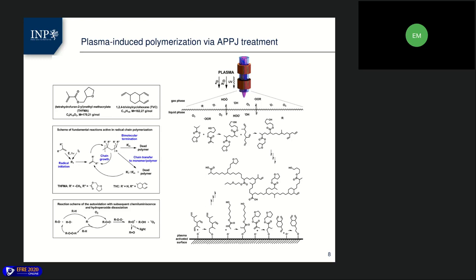Another explanation of larger content of oxygen functionalities in the near surface region of the films could be a higher oxidation degree due to direct interaction of plasma with the surface. The TVC film had about 10% of oxygen in its bulk, whereas the TVC itself didn't contain any oxygen at all. This makes oxygen incorporation into carbon chain of the polymer evident.